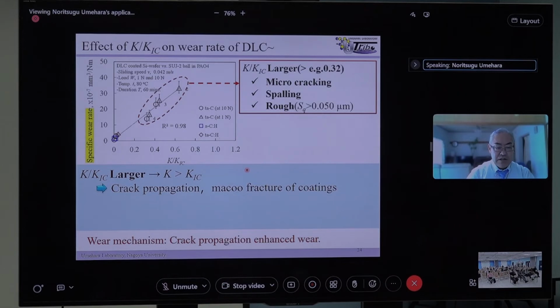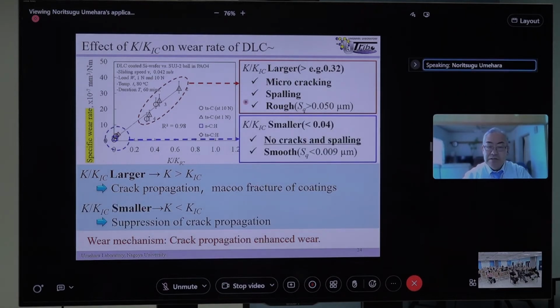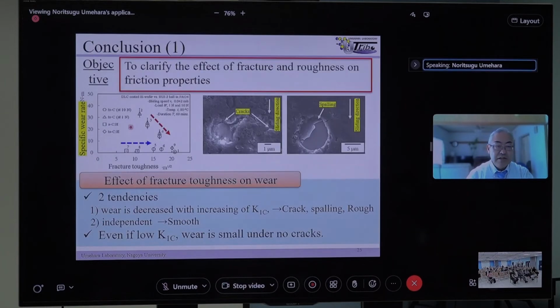So this is the summary. If K by K1C is large, microcracks are generated. But if K by K1C is small, there is no microcracking. That's why we could get a very small specific wear rate. So these are the conclusions. First, good observation could show the two tendencies, and it depends on the fracture toughness of DLC or not.